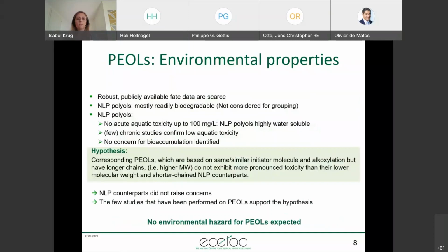For the environmental properties, robust and publicly available data are scarce regarding the environmental fate data. But for NLP polyols, several endpoints are covered, and they are mostly readily biodegradable. And also for the NLP polyols, it was shown that no acute aquatic toxicity up to 100 milligram per liter was observed, even though the NLP polyols are highly water soluble. And in the few chronic studies, also low aquatic toxicity was confirmed. Therefore, no concern for bioaccumulation was identified.